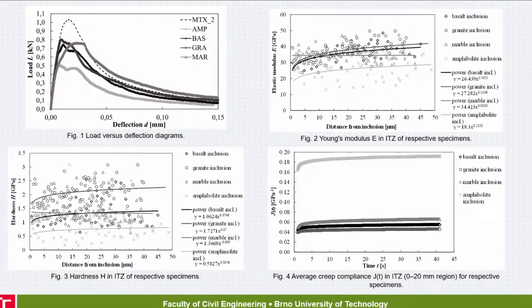After fracture tests were performed, fracture surfaces were examined via nano-indentation technique. So Young's modulus E in the ITZ was measured. You can see it in figure 2, and also hardness H in the ITZ, which is in figure 3, and also the average creep compliance function in the ITZ region was calculated.